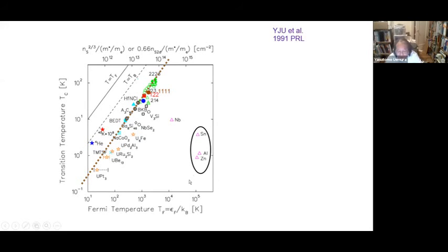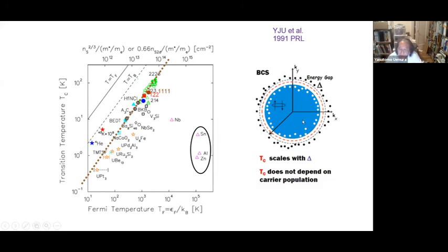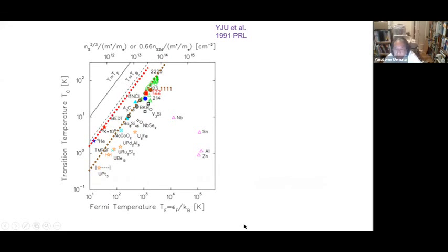And also the Fermi temperature, for example, they are about the same for tin and aluminum and zinc, but TC is different. So there's no correlation between Fermi temperature and TC. So as I mentioned earlier. Now, another thing we can do is, of course, since we obtain the number density of carrier and mass, we